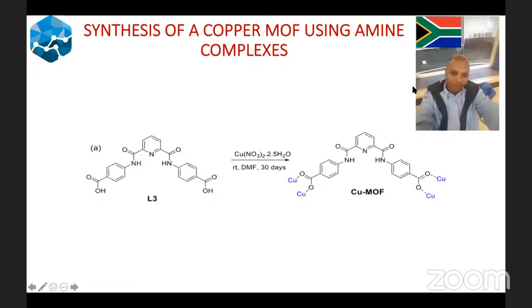As you can see here, this is one of my PhD students. This is Malaza Spelele. She's currently tying up her work. She then managed to synthesize this amine complex, and then, of course, under appropriate conditions, with copper in DMF for 30 days. You can see this reaction took very long because this was a solvent evaporation technique. And already in this complex or ligand, you can see that we have the NN functionality, which is here, which can allow you to synthesize a pincer complex inside the MOF.